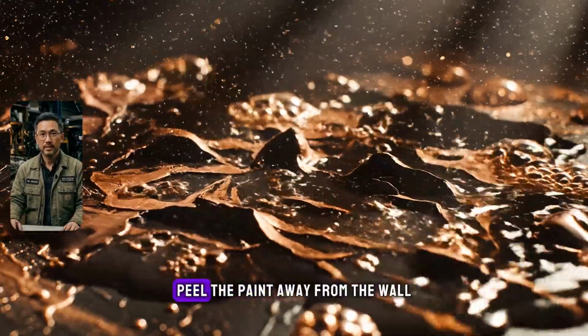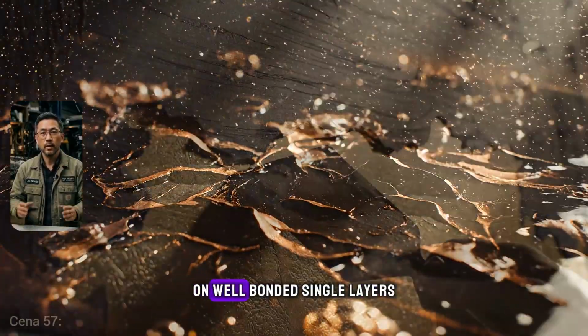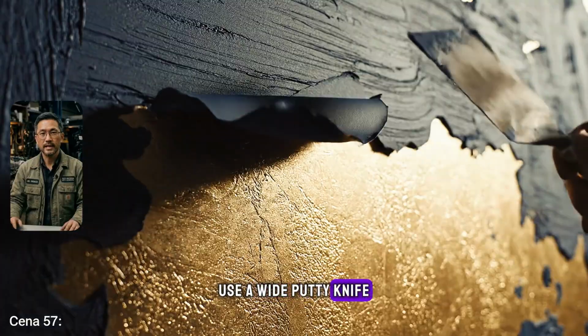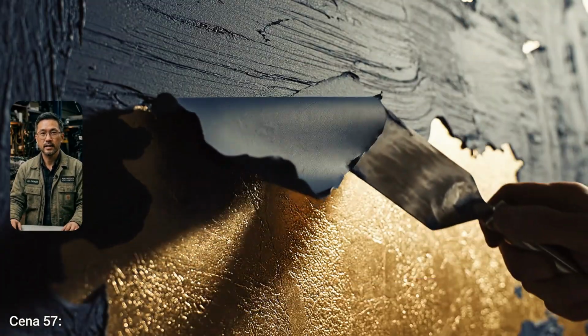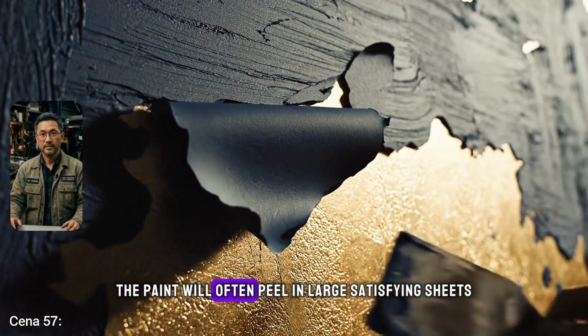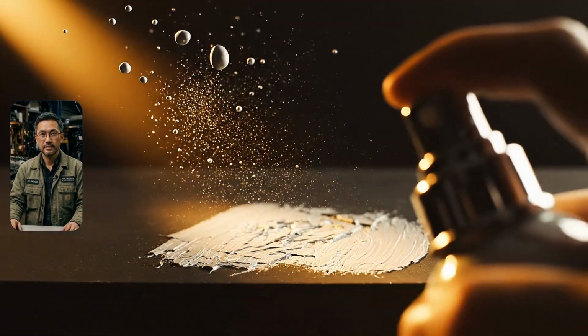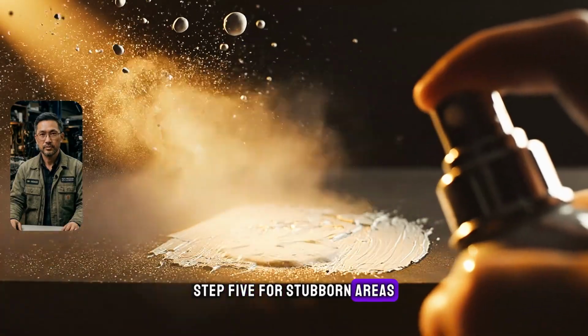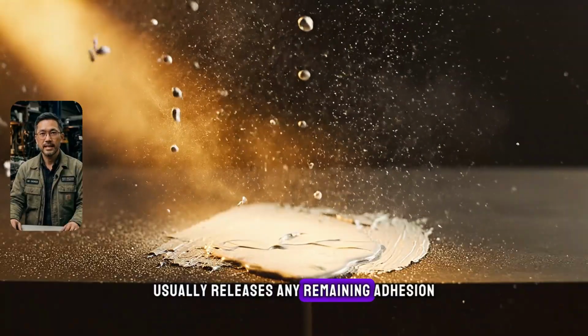Step 4. Starting at a bubbled edge, peel the paint away from the wall. On well-bonded single layers, use a wide putty knife or drywall knife to lift the leading edge. On multiple thick layers, the paint will often peel in large, satisfying sheets. Step 5. For stubborn areas, respray and wait another 5 minutes. A second application usually releases any remaining adhesion.